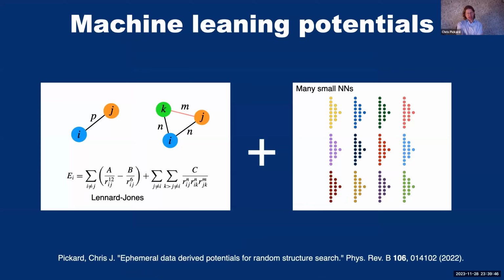So the basic idea behind the potentials that I've derived, now there are a large number of other machine learning potentials on the market, as it were, at the moment, but my interest was on simplicity, ease of training, and robustness. And so the approach I took was based on an observation that we'd made in our group that Lennard-Jones style potentials are actually rather good at identifying different crystal structure types, binary or ternary. So the types of structures can be represented quite straightforwardly with these simple potentials. The relative energies of the phases are not very well described, but the structures can be described. So I looked to develop a potential based on the very simple Lennard-Jones form.